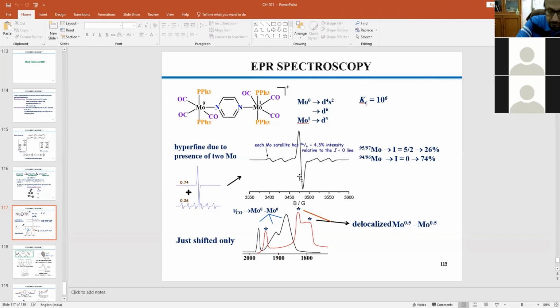Now, if it is localized on one particular metal center, then you should expect 3 lines here, 3 lines here. If you very carefully look at this EPR spectrum, you have to be very critical, and if you do some scale checking, you will see 1 line, 2 lines, 3 lines here. Let me show you. 3 lines here, 1 line here, 1 line here. 2, 3, 4, 5, 6, 7, 8, 9, 10, 11 lines are there. So apparently, if you look at this EPR, you will feel that only one moly nucleus is interacting with the unpaired spin. So that means the 2 molys are identical.